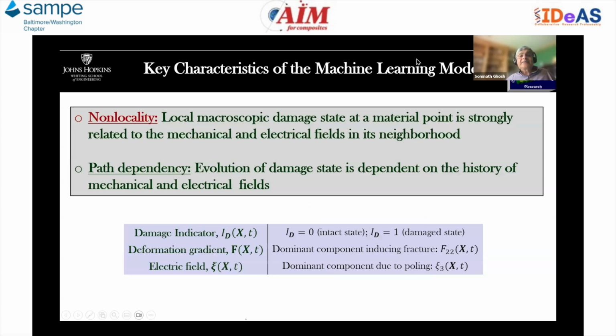The key characteristics of the machine learning model: the local macroscopic damage state at a material point is strongly related to the mechanical and electrical fields in its neighborhood. The path dependency: the evolution of damage state is dependent on the history of the mechanical and electrical fields, and this is very important. So there are three macroscopic fields that we are going to probe as full field variables. One is the damage indicator, ID equal to 0 corresponds to the intact state, ID equal to 1 is a damaged state. Then the deformation gradient as well as the electrical field.